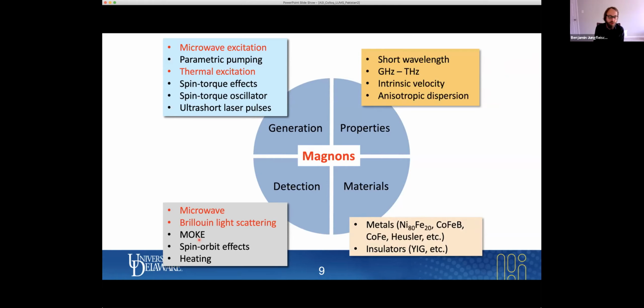Material-wise, well, we want to transfer spin angular momentum encoded in magnons. So this means we are interested in a long decay length, and this means we are interested in materials with a low Gilbert damping parameter. So typically, the benchmark material is yttrium iron garnet, YIG. That's an insulator. YIG is beautiful. You can do wonderful experiments with it. The disadvantage is it's pretty hard to nanofabricate yttrium iron garnet. It's pretty challenging. It's doable, but challenging. Much more straightforward is to use metals. And metallic materials with a low Gilbert damping parameter are nickel iron, we call this permalloy, cobalt iron boron, certain cobalt iron alloys, and Heusler alloys. Today I'm going to use nickel iron, so permalloy, and cobalt iron.